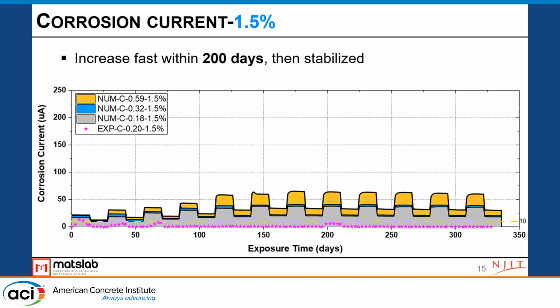Another observation is we can see the corrosion actually increasing fast within around 200 days. And after that, it starts to stabilize. It's not increasing significantly after a certain time. And also from crack width of 0.18 to 0.32, the increase of crack width is kind of big. However, we didn't see the corrosion increase proportionally to the crack width. As we see here, the gap is relatively small between the 0.18 millimeter crack width and the 0.32. So we can say the critical crack width for this specific chloride concentration is between 0.3 to 0.6 millimeter.